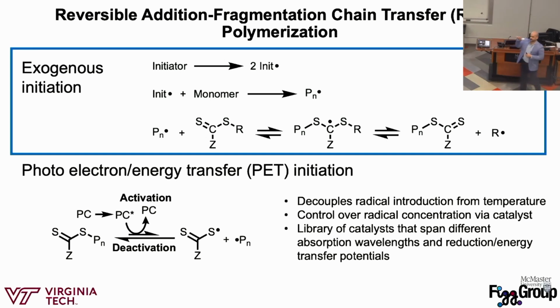So my group likes to take advantage of reaction kinetics to access different sorts of structures. If you can access a different energy barrier by changing the temperature, but you're not changing the concentration of radicals in the solution, you can think about synthesizing more precise structures by playing with the kinetics of what's going on in solution, while not changing anything else except the temperature and how that temperature is affecting the reaction pathway. You're not changing radical concentration or anything else. So we love that. That's what we think about a lot.